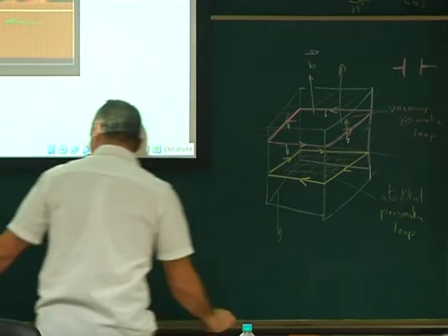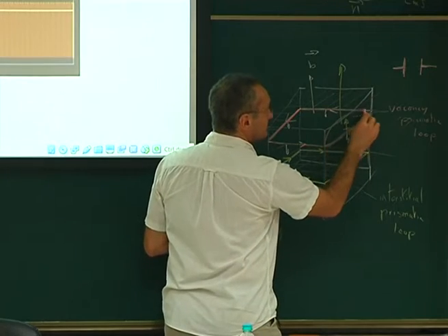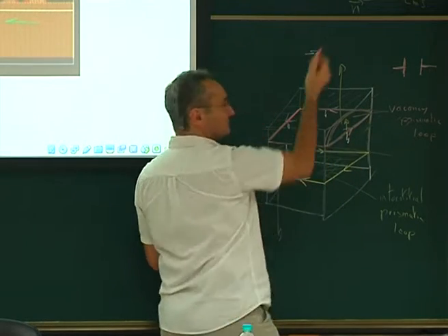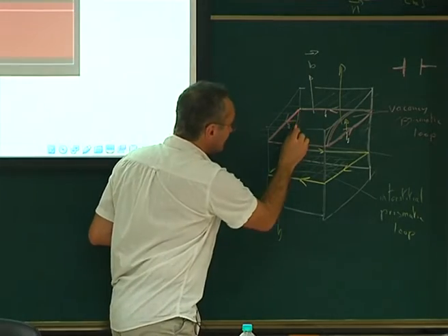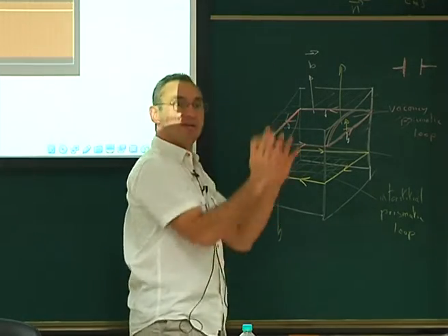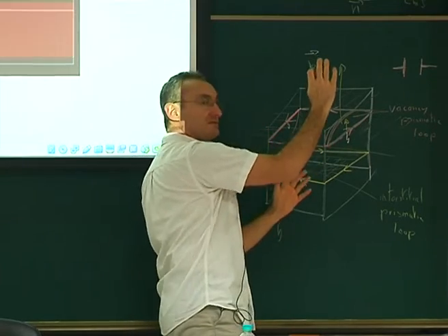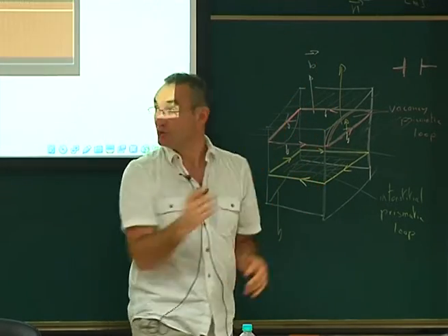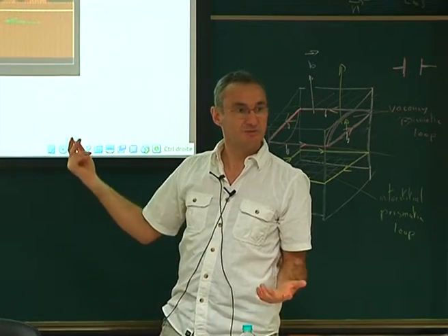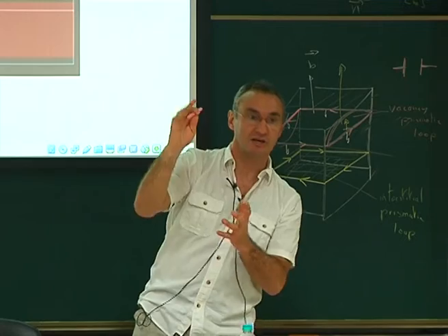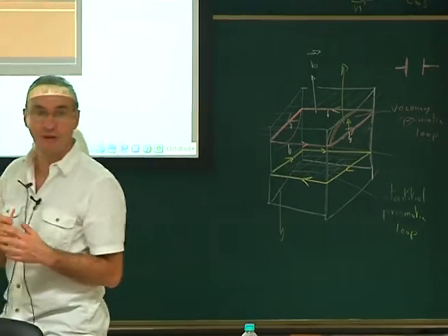So it means that this line will move up, let's say like this. It will go upstairs. But this one is negative, so this one will move down. Exactly. So finally, the loop will get inclined. The loop will not glide, it will get inclined. One will go up, one will go down, and it will be immobile. So here it's not immobile, it is gliding. So why is it so? Something is different here. Why is it gliding and not inclined? Do you have any idea how this could happen?